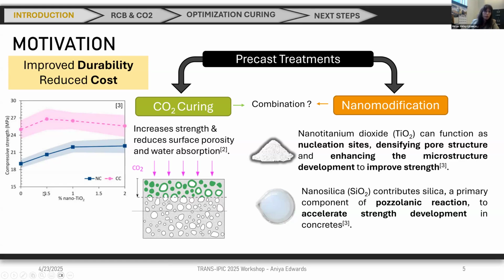So with 0%, 0.5, 1, 1.5, and 2%. So we see that the use of titanium dioxide increases the strength, nothing new. And if we do CO2 curing with no titanium dioxide, we have an increase. Now, if we put 0.5, we have a similar increase, and now it's lower and lower. So we have to be careful, because adding these two approaches together is not just adding the two benefits together. Having said that, especially in this case, with 0.5% of titanium dioxide, we have the highest value, which is much higher than just not using titanium dioxide and not doing CO2 curing.